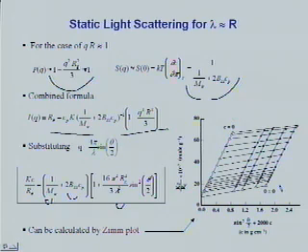So you do a set of measurements at different concentrations and different theta angles. In the previous experiment, the theta was constant, but ideally it would be small. In this experiment, you vary both theta and concentration C, in order to obtain three parameters: inverse molecular weight, second virial coefficient, and radius of gyration.